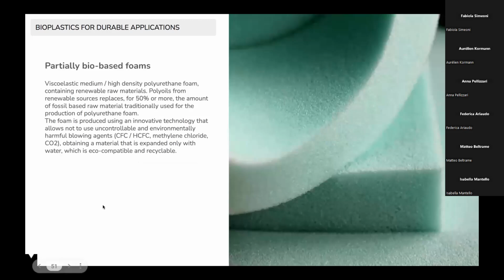When it comes to foams, there are partially bio-based foams available, typically the polyols in expanded polyurethanes in blocks. The polyol part can be bio-based. Also, in this case, clearly the price is higher, not super higher, because it's a commodity material, and a broad number of polyurethane manufacturers provide this type of solutions. So there is also some type of competition. And in that case, you will have a partly bio-based content, and that would work for the carbon footprint of the material, basically. Otherwise, it's exactly the same type of material with the same problems in recycling, etc.